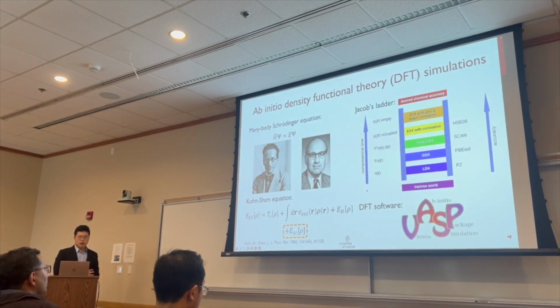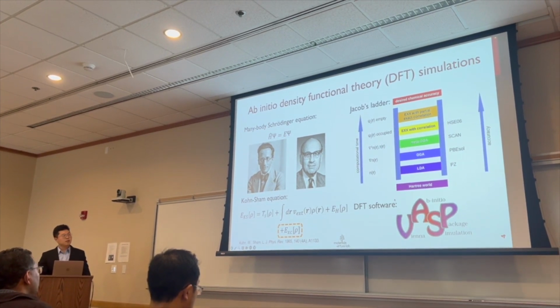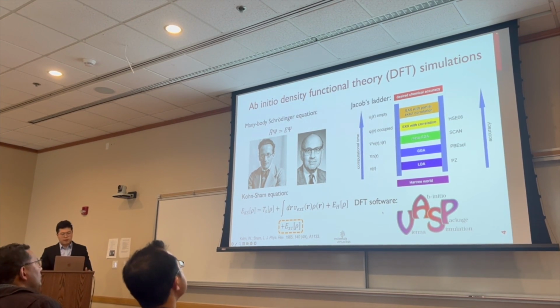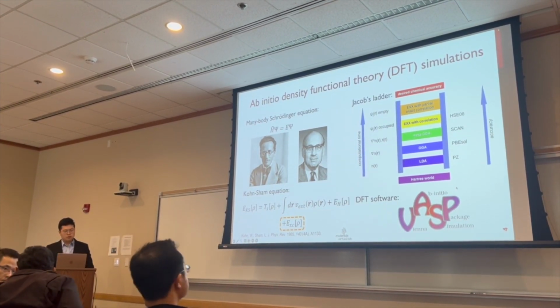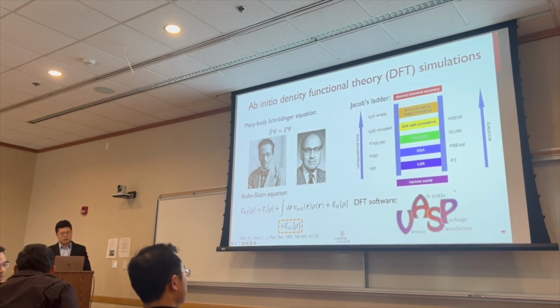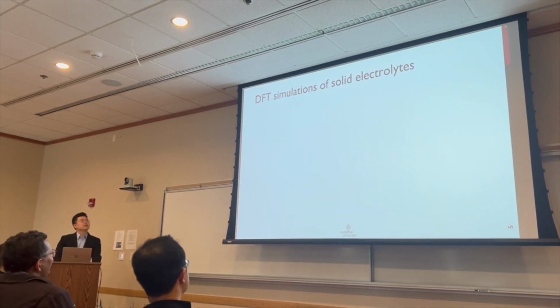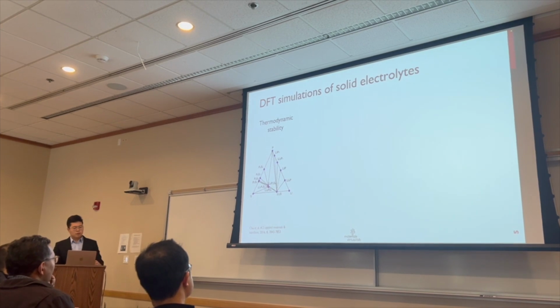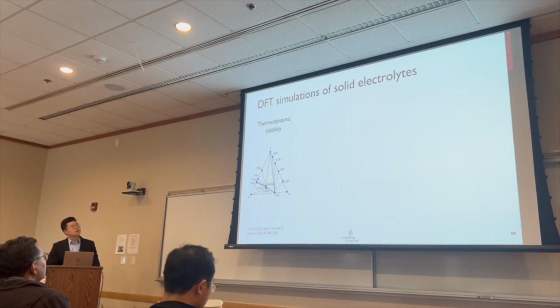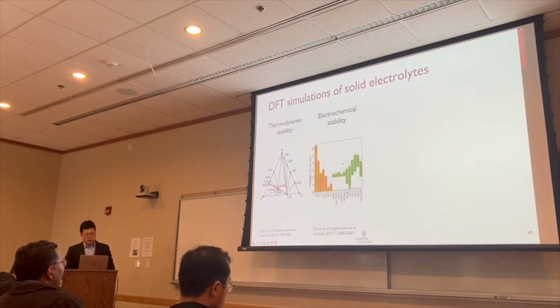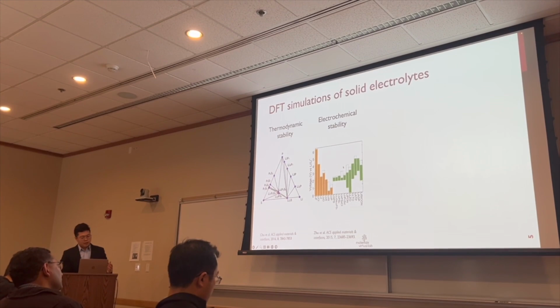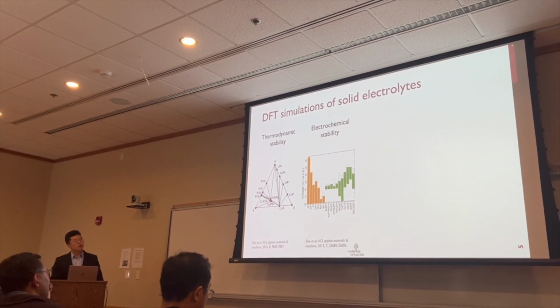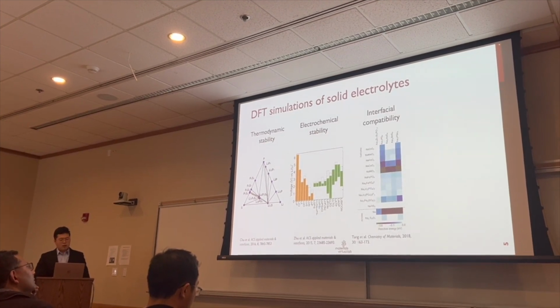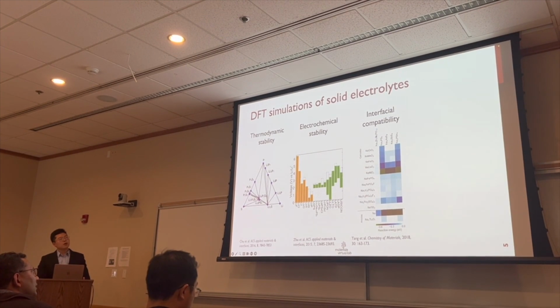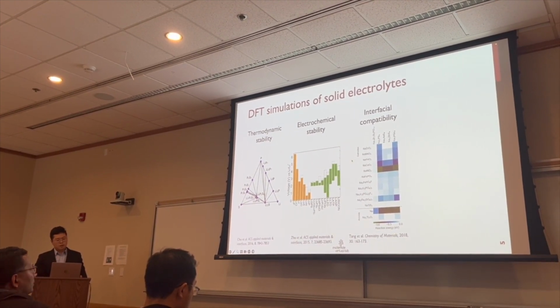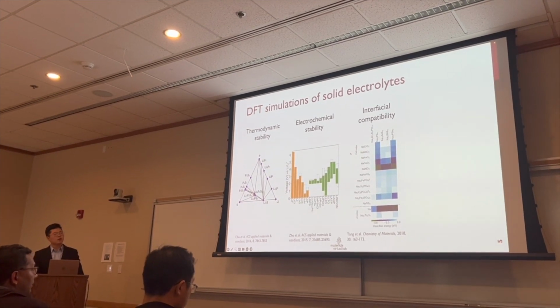And most of those density functional methods, or different functionals, are implemented in the very famous DFT software called the Vienna ab initio simulation package, which is ready to use for computational material scientists to study different systems. And specifically for solid electrolyte materials, from the results of density functional theory calculations, we can construct the phase diagram to study the thermodynamic stability of solid electrolytes. And we can also construct a grand potential phase diagram to analyze the electrochemical stability window for those electrolyte materials. And we can also calculate reaction energy for electrolyte material versus different electrodes for us to come up with a good combination of materials for the whole cell.